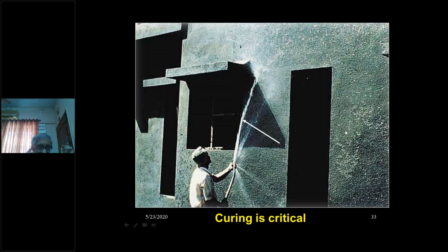One important lesson I have learned is that curing is a must. You cannot neglect the curing because it is the last step of concrete making. Curing is very, very important. It increases the life of the structure because with good curing, you can gain strength of the concrete, even of the plaster. If a well-cured plaster without cracks is there, it can even afford some protection against future corrosion of bars, etc. It may not give you the strength a structural member gives you, but it can give you the protection which otherwise would not have been there if the plaster were not existing or if the plaster was badly constructed and cured. I'll give you one example.